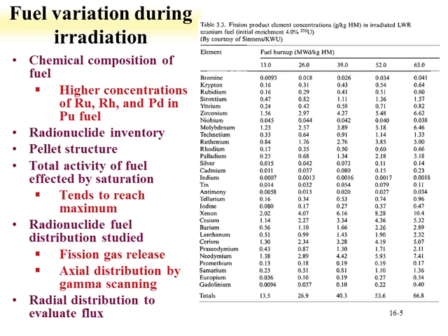And some of the important fission products that we see here include xenon. At a low burnup, it's 2 grams per kilogram of heavy metal, going all the way up to 10 grams. Xenon also has large neutron capture cross-sections, which is responsible for some poison behavior in fuel. After xenon, we would see molybdenum, which also has relatively high amounts, again, a gram per kilogram heavy metal at a low burnup, up to 6 grams per kilogram at higher burnups.